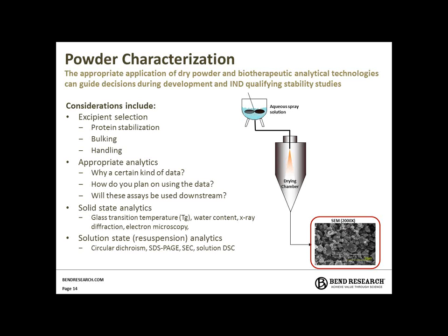As Devin was mentioning, water content for biotherapeutics is critically important to understand and perhaps modulate. We routinely operate at the very low end of water content, around 2 to 4% by weight. We need to understand what that water content may or may not be doing to the biotherapeutic itself. We need to understand how the excipients organize or don't organize in the solid state, and X-ray diffraction helps with that. We also routinely just want to see our particles, and the SEM will do that as well.